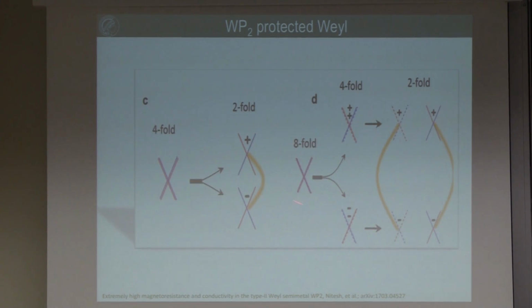So here in tungsten phosphide 2, we have a very special situation. It's not like in a normal Weyl semimetal, which you can think about as coming from a Dirac point, which is split into the chiral two-folded Weyl points. Here we have a higher situation because of the crystal structure symmetry. We have a higher degeneration, so we can think about our Weyl semimetal coming from an 8-folded Dirac point, which leads to this configuration.